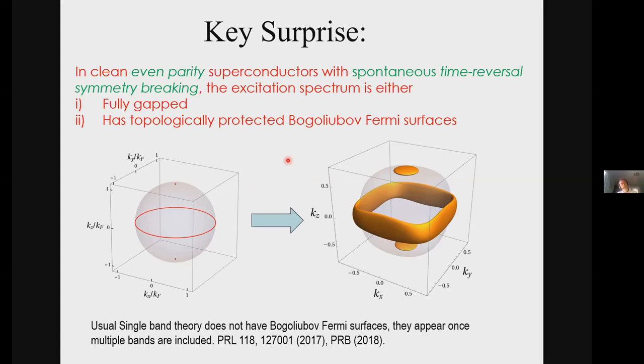Maybe in strontium ruthenate related cases, this depends quite a bit on the role of parity symmetry in your theory and whether you have Wannier functions that are centered at sites of inversion symmetry or not. If they are centered at sites of inversion symmetry, then I think, yes, spin-orbit plays a key role. But if they're not, I think you can have other interactions that drive these Fermi surfaces. I see. Thanks.